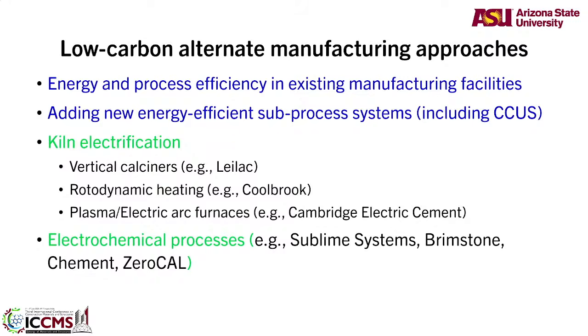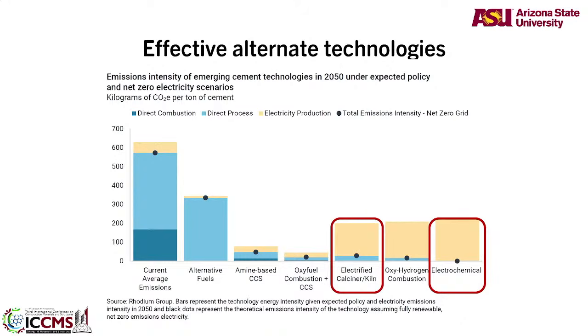Now, I'll show you a few ways that you can tweak this whole process, and there is plasma as well. So here is current average emissions, just to set the stage, current average emissions from cement production. This is direct combustion. These are the direct process emission, which is your calcium carbonate becoming CO2, and this is electricity production, right? If you use alternate fuels, you can take away all this fuel part, you just drop it down to this part, and then amine-based oxy-fuel. But if you do an electrified calciner or kiln, you take this thing off completely. You have lots of electricity need, but this process emission is gone completely, assuming that, now that's a key here.